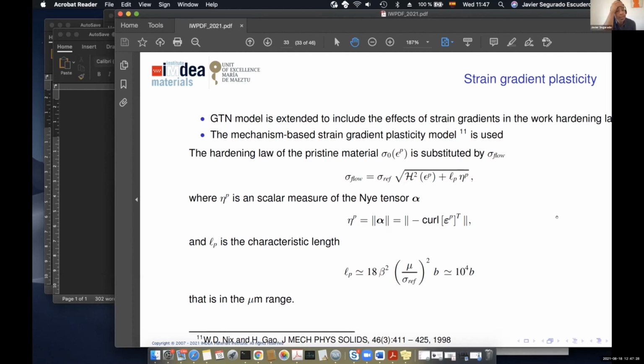So the good thing about FFT is that, different from finite elements, you evaluate the fields, stress and strain, at the same point as the internal variables. So using the same field operators that you use to obtain the PDE, you can also derive the internal variables without making any trick like what you do in FEM. In this case the problem is lower order, because what we do is to obtain the curvature and plug it into the constitutive equation. In the case of the damage model, we obtain the gradient, but in this case, it's a higher order model. So we solve in parallel two PDEs. We have a specific boundary condition for the non-local variables, and we have a staggered, fully implicit approach. In the case of plasticity, we didn't think it was necessary, and it simplifies things to do it that way, especially in the case where we mix all the models in one.